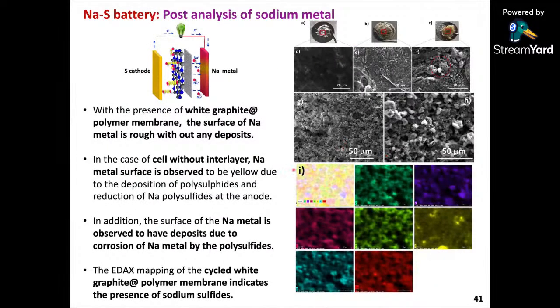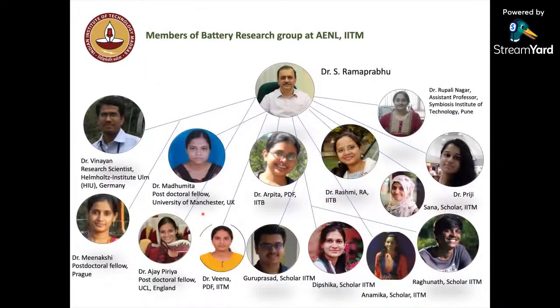So in order to do the post analysis of the sodium metals we have done, you can see that this is the presence of the interlayer. The surface of the sodium metal is rough without any deposit. Whereas if you see this cell without interlayer, sodium metal deposition is observed. You can see the yellow color on this, due to the deposition of your polysulfides, and here also corrosion occurs.